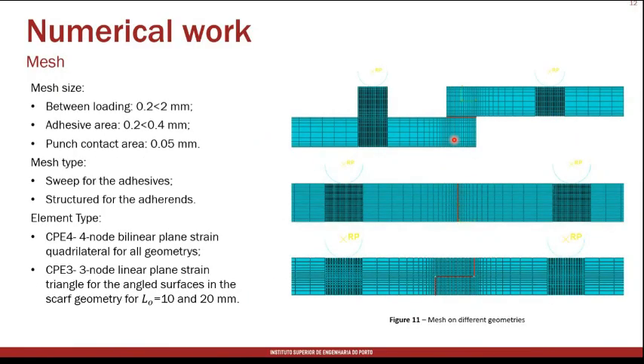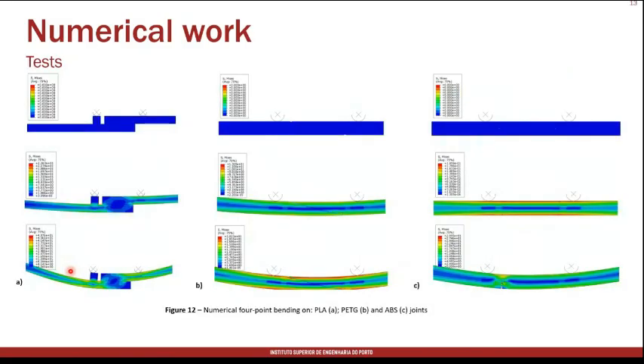Some details about the mesh sizes, the bias effects that were used with a more refined mesh near the crack propagation region, and the type of elements that we used, which were mainly plane strain elements, CPE4 and CPE3 for the sloped surfaces of the scarf joint, and a cohesive element with 4 nodes for the adhesive layer partitions of the model. Here we can see some deformed shapes, one for each type of joint. We have a single lap joint, we have a scarf joint with an overlap of 20 millimeters, and one step joint here showing the beginning of failure in the adhesive layer.